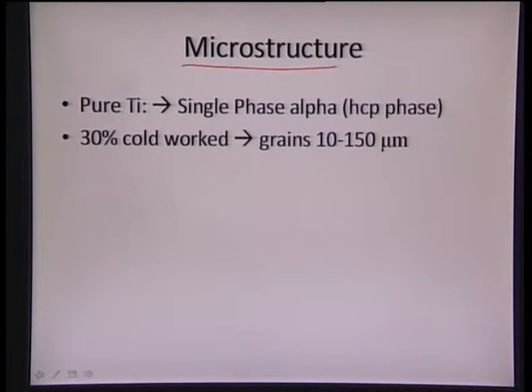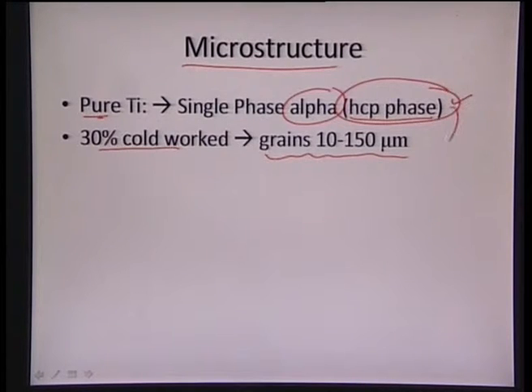Coming to the microstructure, pure titanium is hexagonal HCP, and the phase is called the alpha phase. So pure titanium is more of a single phase material, and it is HCP. Owing to the limited slip planes available in an HCP crystal, it has very limited processability, so it is generally very difficult to process. This titanium is generally cold worked to achieve grains in the order of 10 to 150 micrometer in size. Ideally, we get a single phase structure, and to induce more strengthening, approximately 30% cold working is given in order to achieve grains of 10 to 150 micrometer in diameter.